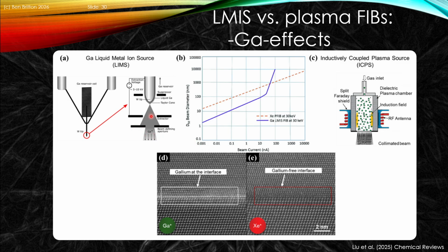So we can see this in terms of the spot size and currents. We can see this in terms of how we get different resolutions. This is a related picture to what we had. But one of the reasons why we might want to avoid gallium in our system is that gallium can collect on the interface when we prepare this. This is an atomic resolution, I think it's a STEM image of a system. And so here this gallium can enrich itself, and so we get a sample preparation artifact due to the decoration of gallium at this interface. If we prepare the sample with xenon FIB, we see that we do not have that enrichment of gallium. And so this is one example where there is an improvement because we don't have sample prep induced defects in our system.